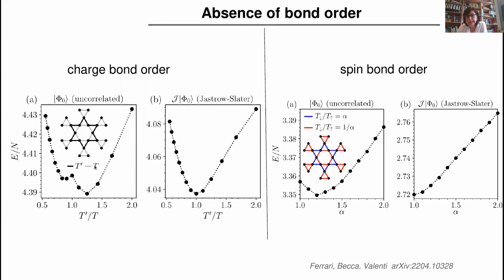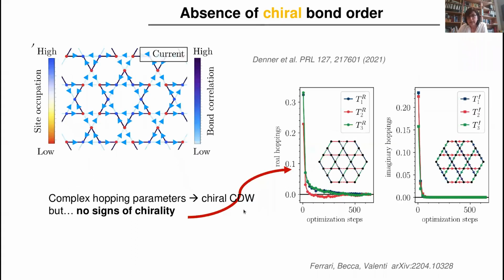Moreover, we tried to investigate whether there is some kind of chirality in these different bond orders. But let me show you again this point: introducing more correlations into the system, more fluctuations, washes out some of the phases present at the mean-field level. For instance, at the mean-field level we do get this Star of David. As soon as you introduce the Jastrow-Slater factor, this phase becomes unfavorable. So you don't get this type of charge order, and the same for the spin bond order. What about the chirality?